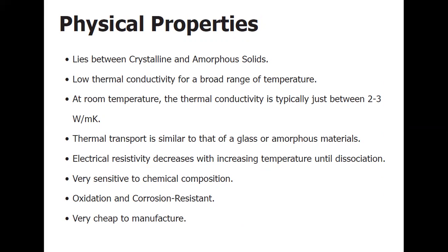Electrical resistivity in quasicrystals decreases with increasing temperature until the material dissociates, which typically happens at around 1000 Kelvin. The magnitude of the electrical resistivity remains pretty much unchanged throughout this temperature range, typically just changing by less than 30%. Quasicrystals are also very sensitive to chemical composition. A very minute and slight change in its chemical composition can severely affect and influence transport and physical properties.